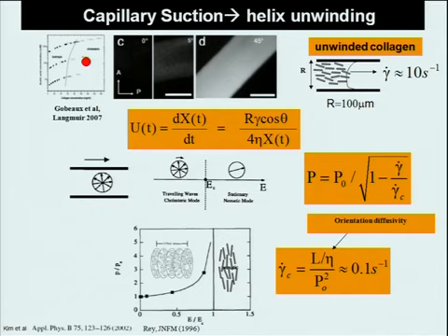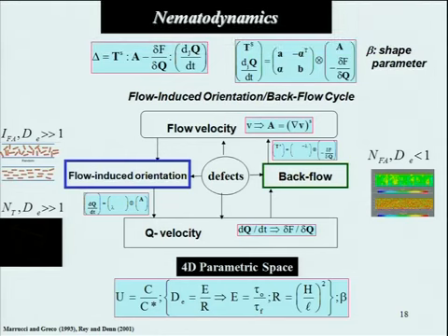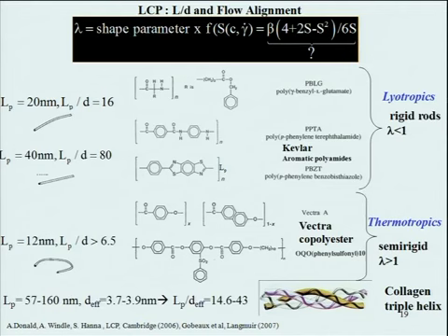So you have traveling wave modes, and so this thing is rotating and is expanding. And so this process of expansion gives you a divergence of the pitch at a critical shear rate, which scales with the orientational diffusivity. So you have a lot of shear rate in the system to melt the helix and turn it into a nematic.